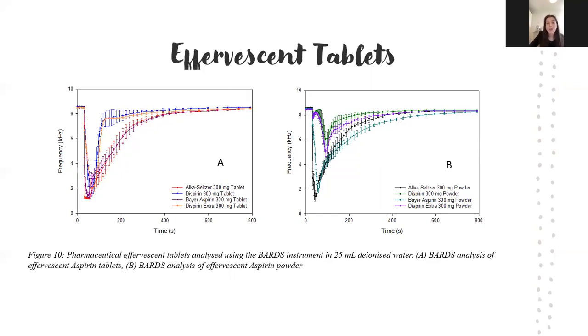And then Disprin Direct and Disprin Extra are also from the same company and perform identically in solution. However, there's a difference in API content for both of these. They're all highly reproducible. The two Bayers, there's only 24 milligram difference in API, which is relatively insignificant. As you can see, they perform identically in tablet and powder form, whereas the Disprin formulations actually have a 200 milligram difference in API content.